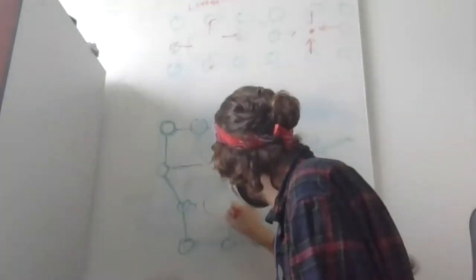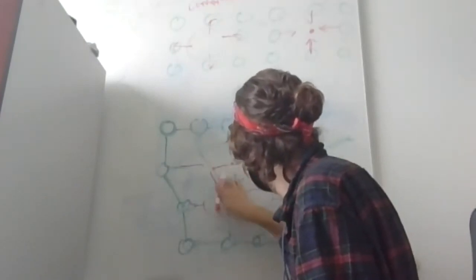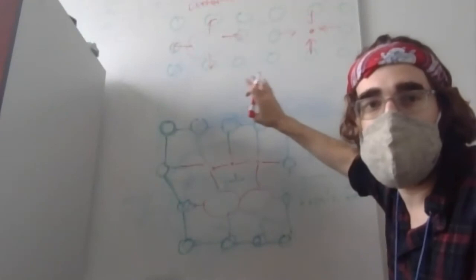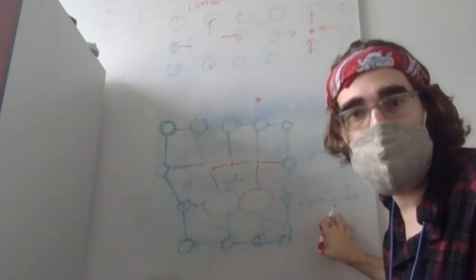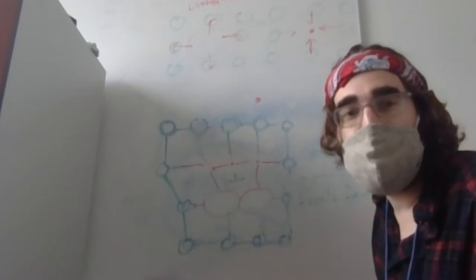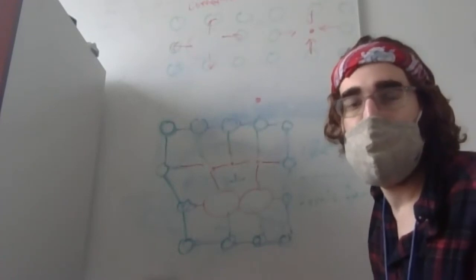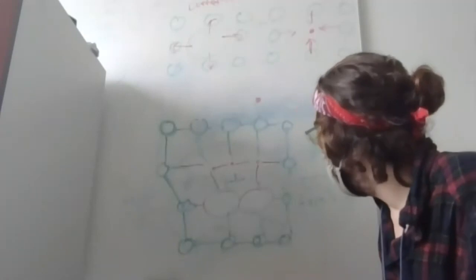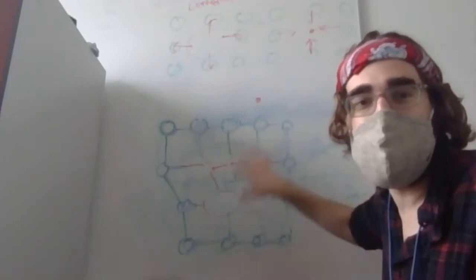Likewise, below the dislocation, we would have the big atoms diffuse. So now the big atoms that introduce compression will reside in regions of tension. And by just trying to lower the energy states, atoms will naturally diffuse to these regions. And so what happens is dopant atoms, dopant ions, alleviate the stresses introduced by edge dislocations, right?